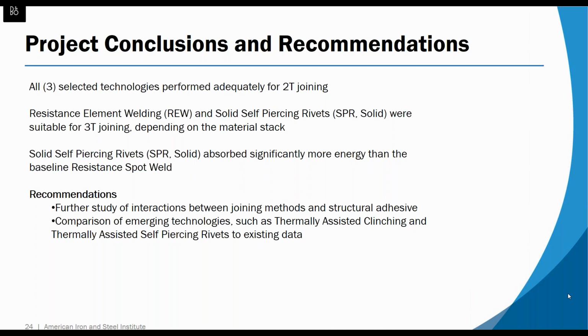Our conclusion: first, from a two-thickness standpoint, all three technologies performed adequately for our needs. For three-thickness joining, both resistance element welding and solid self-piercing rivets worked, but there is a caveat that they are somewhat sensitive to the stack-up, so stack-ups will have to be validated for any given application. That's not really any different than resistance spot welding, though.